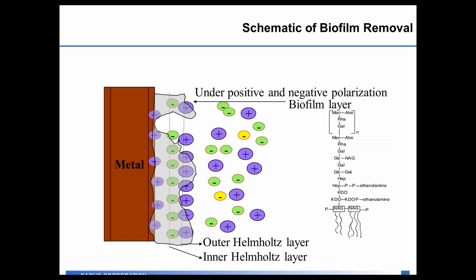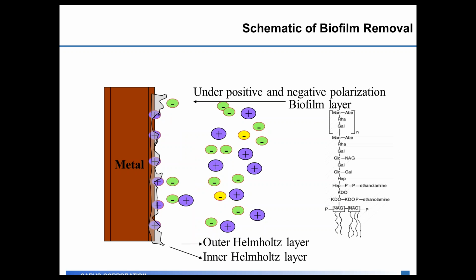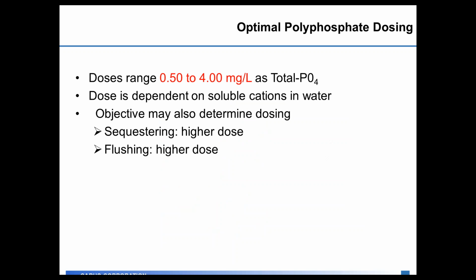As the polyphosphate removes those metals from the biofilm, it punctures little holes in the biofilm, allowing your chlorine or chloramine residual to get deeper and deeper penetration into the biofilm. What this shows is that over time, as you remove those metals from the biofilm and you maintain your chlorine and chloramine residual, you're able to clean up that biofilm and remove it from the distribution system and prevent any issues that that biofilm causes in the distribution system. It's one of the reasons why polyphosphates are fed in the distribution system, because you can help clean up that biofilm and scaling you have in the distribution system over time.